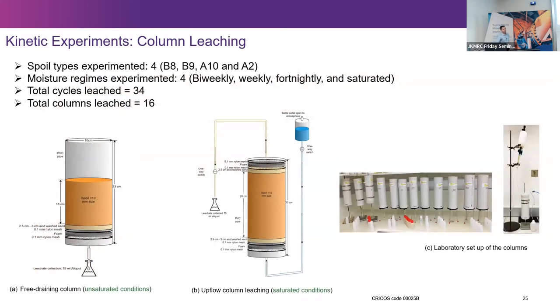And then we moved on to kinetic experiments. So we designed some column leaching experiments customized to understanding salt release. The traditional approach is based on AMD. Column leaching experiments are carried out by industry as a standard practice to understand the kinetic behavior of the materials. But we wanted to get an understanding of moisture regime, how moisture would impact salt leaching. So what we did is we tried four different spoils, and we also experimented with four different wetting regimes. That is, we were wetting one set of samples biweekly, one set weekly, one set fortnightly, and one we just kept saturated throughout.